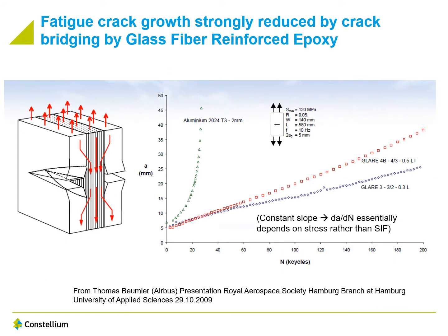The basic principle of fiber metal laminates, why they are very good in fatigue crack growth, is that the loads or the stresses in the metal sheet are transferred by crack bridging to the composite made of epoxy matrix and glass fibers.